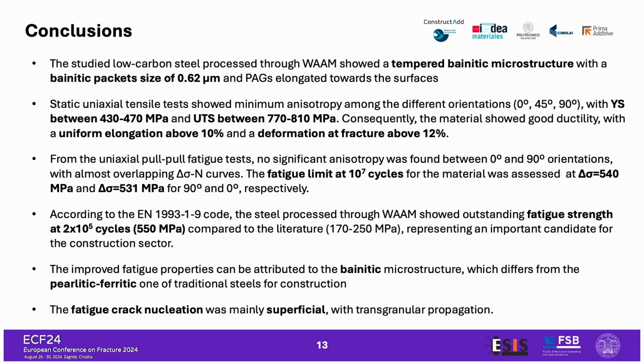So just to conclude, we processed our low carbon steel with one technology, and we obtained a very fine bainitic microstructure. We assessed no anisotropy in a static condition, both regarding the yield strength, the UTS, and also the ductility, which was very high, so above the 10% regarding the uniform elongation. We assessed through the fatigue test the fatigue limit at 10^7 cycles being delta sigma of 540 and 531 megapascal for the 90 and 0 degree configuration.